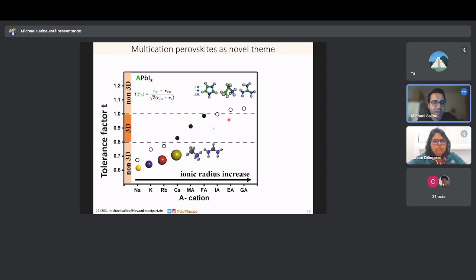So if you know any cation which could fit in the in-between spaces, I'd be very curious. I didn't know of any of them. I was looking very hard throughout my PhD and postdoc time as well, but I couldn't find any of them. So for lack of finding them, in literature, people then started to mix the cations together in order to get an average, which is in between, in order to find the sweet spot where you can use multiple cations together to have a good tolerance factor, but also a good composition, because some of these components, like methylammonium, may be unstable. Formamidinium is relatively bulky, so you want to be able to move along this line.